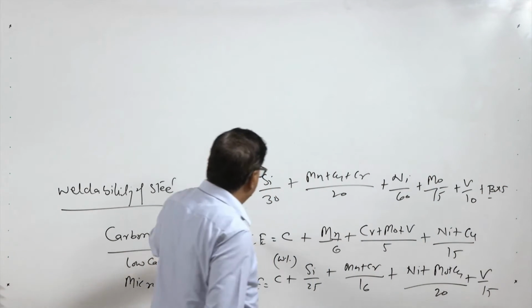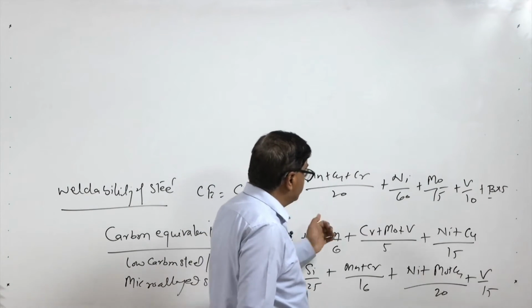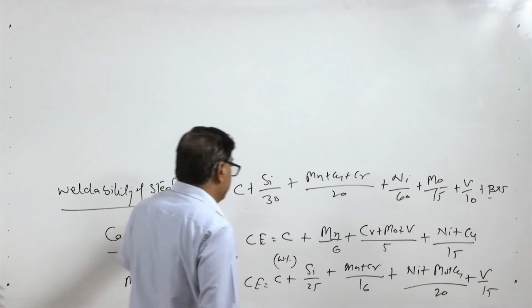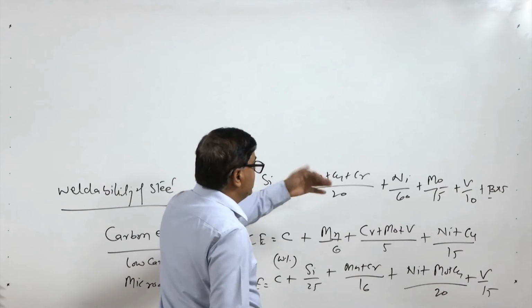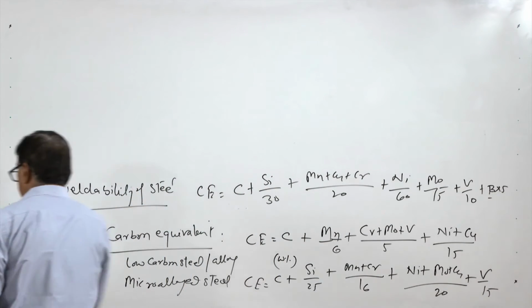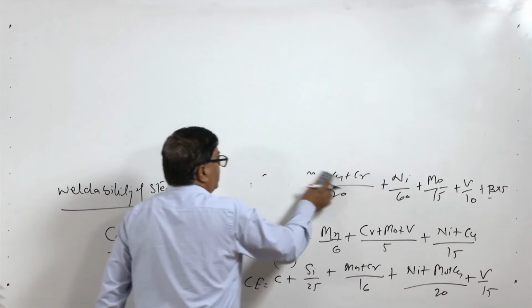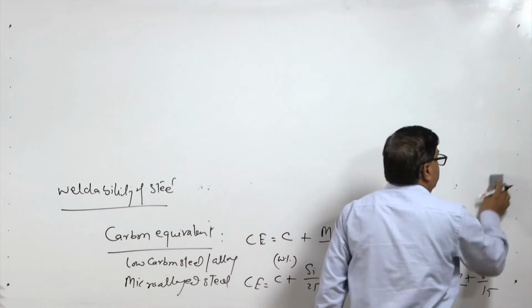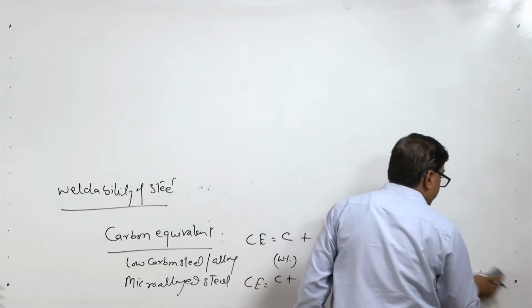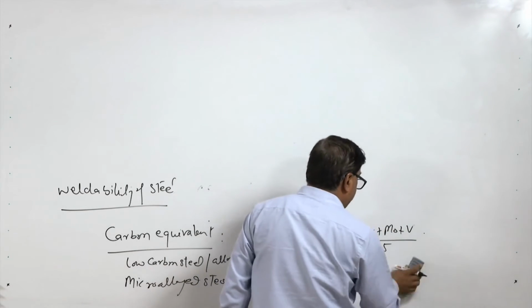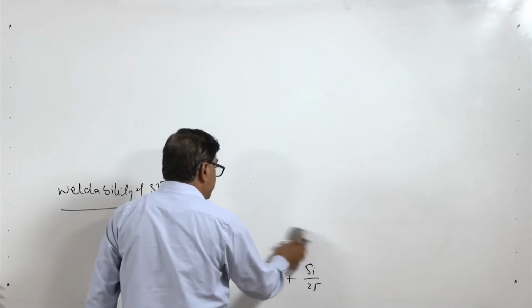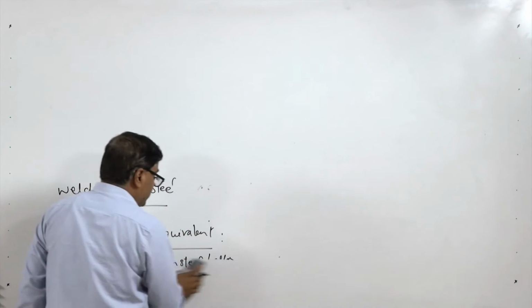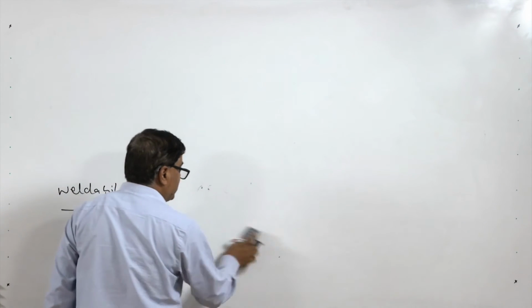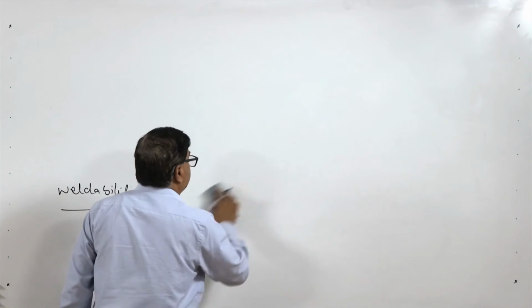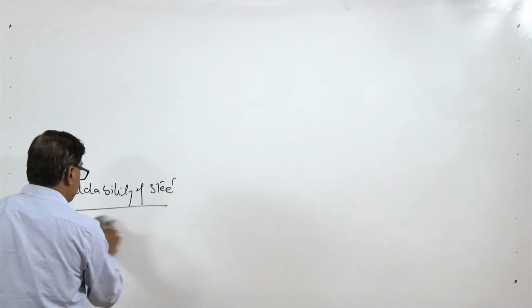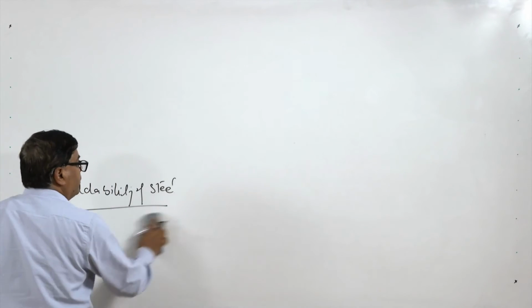So, here the weight percentage of each of the alloying elements in the steel is put in these equations to calculate the carbon equivalent, and the carbon equivalent calculated based on the composition is related with the ease of welding, since the carbon equivalent directly affects the hardenability, and the hardenability of the steel determines the cracking tendency of the steels, which in turn governs the kind of efforts required for avoiding the cracking in terms of the preheating or cooling during the welding.